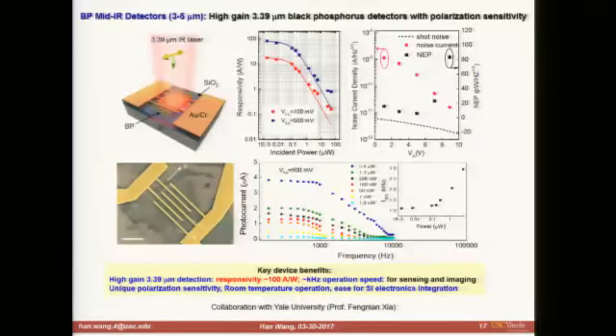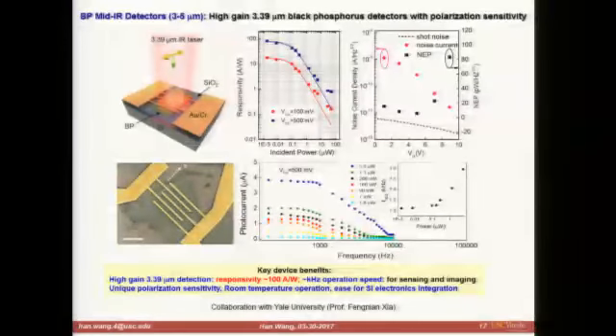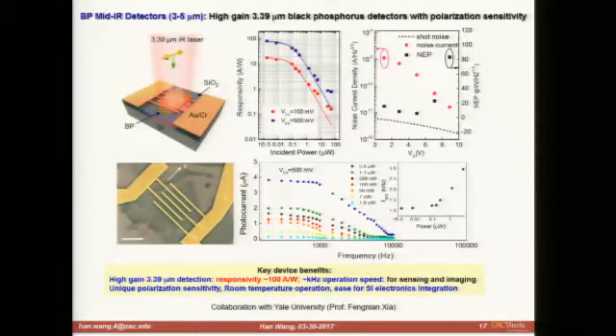Because with just one material, it can cover a very significant portion of the mid-IR region, and also most of the near-IR region. So in order to realize that potential, recently we have been working with our collaborator at Yale on demonstrating a black phosphorus mid-IR detector that works in the 3 to 5 micron wavelength range.